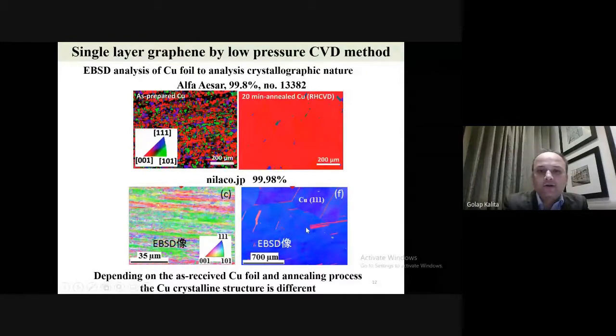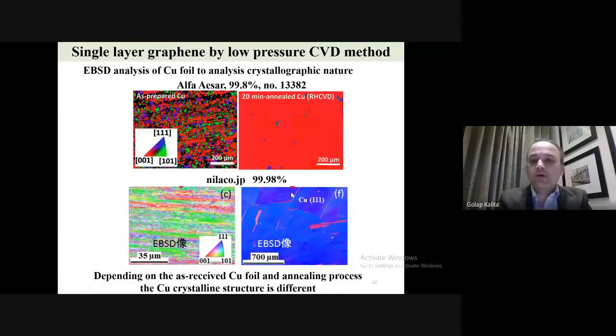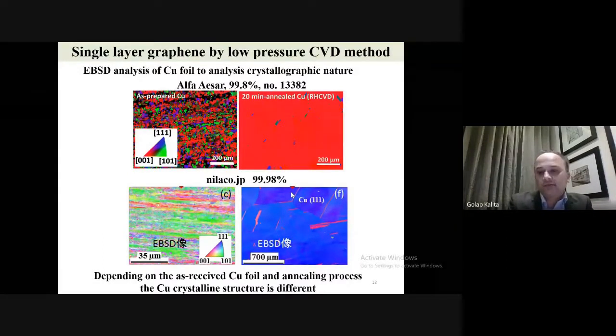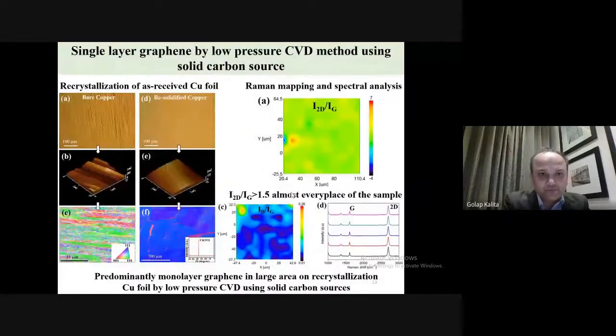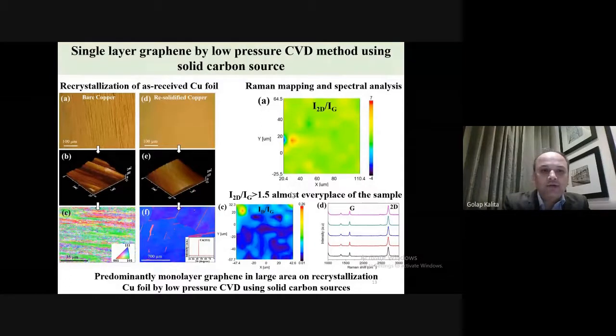On a single crystal copper foil, when you have a single crystal substrate, the nucleation of the graphene domains will have the same orientation. But if you have different grains in the substrate itself, the domain orientation of graphene will be different, and that gives lots of defects in the grain boundaries. So it is always better to have a single crystalline substrate to grow high quality single layer graphene. This is the process. This is the purchased copper foil. Then when we resolidify it, you can see how smooth it becomes. AFM study also shows a very smooth surface, and it becomes single crystalline. On this kind of substrate, we can grow the graphene layer very uniformly with fewer defects.